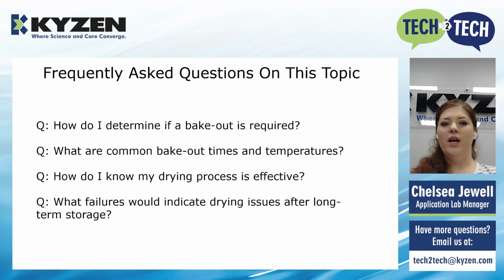So, knowing if your drying process is effective: well, first and foremost, are the boards coming out of the machine dry? Are you seeing pooling in any sections of the board, any complex geometry that's holding water? An air knife or just an air nozzle is a great tool to force air underneath components and drive it out. A lot of times what I look for is that initial spray pattern that will go across the surface from underneath components, from out of connectors. That type of application we use to troubleshoot.